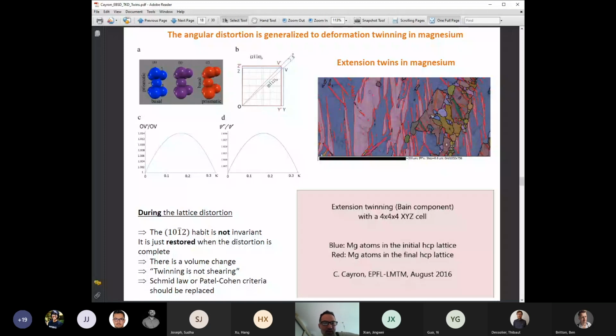And then you realize that, if you look at the details, what is called the shear plane cannot actually be a shear plane, because if you look at some distances, some directions in this plane, they are not constant. They change during the twinning mechanism. When you change the basal plane at the left on the top, I'm sorry, the laser is really missing to me, but